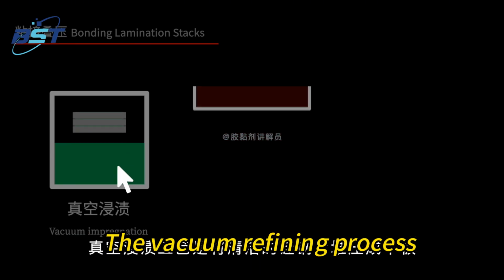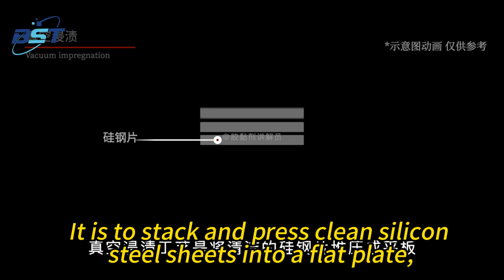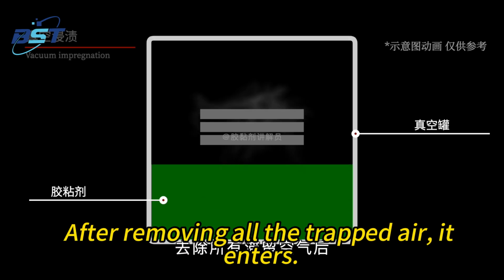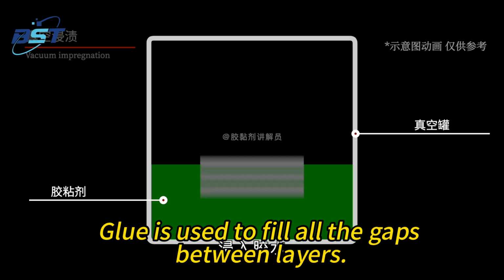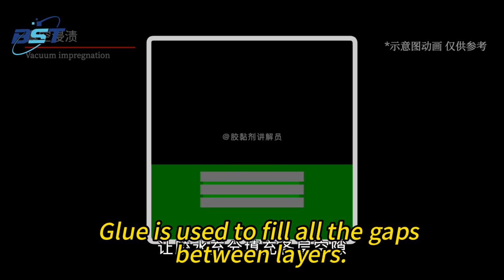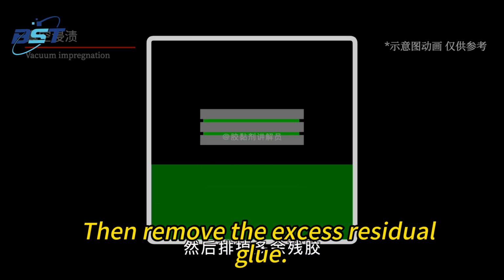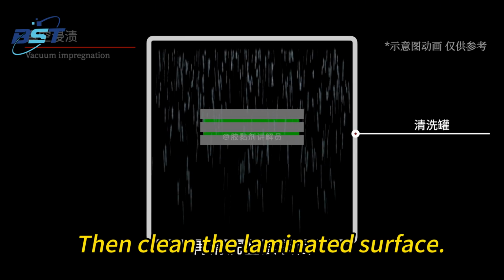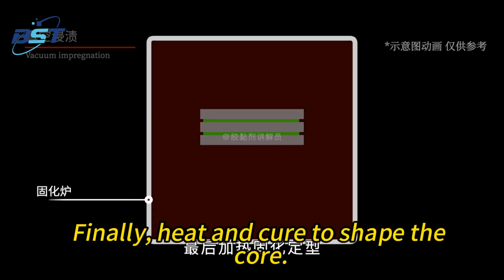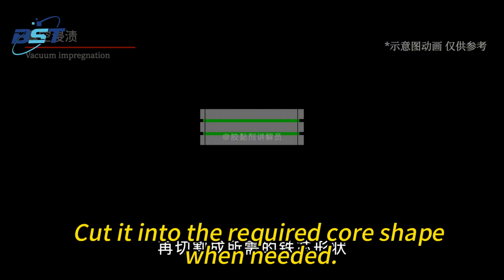The vacuum impregnation process is to stack and press clean silicon steel sheets into a flat plate and put it in a vacuum tank. After removing all the trapped air, glue enters and fills all the gaps between layers. Then remove the excess residual glue. Then clean the laminated surface. Finally, heat and cure to shape the core. Cut it into the required core shape when needed.